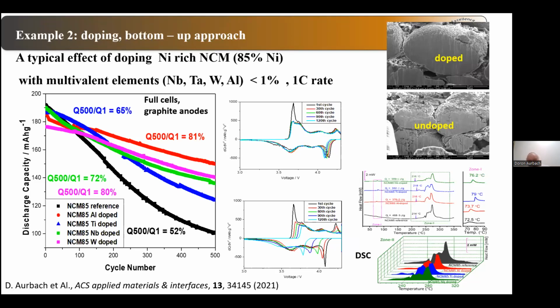calorimetry. We put a measured amount of cathode material together with the standard electrolyte solution, we increase the temperature, and we measure when thermal reactions start and what the heat evolution from the sample is. You can see that indeed, when we have good dopants, like in the case of titanium and aluminum, compared to the reference, the black one here, we see very clearly that with undoped material we have a lower onset temperature, and also the heat evolution is always higher when the material is less stable.